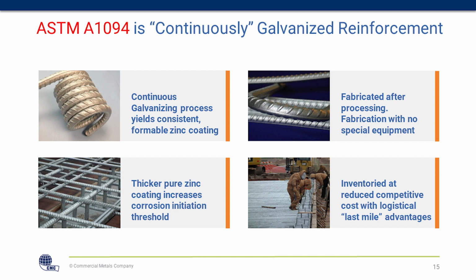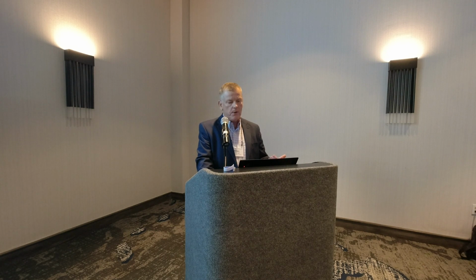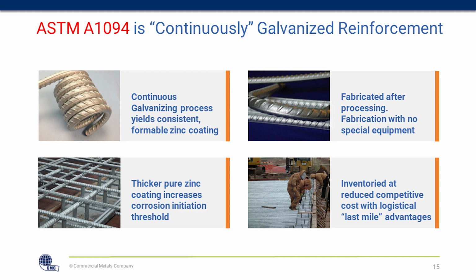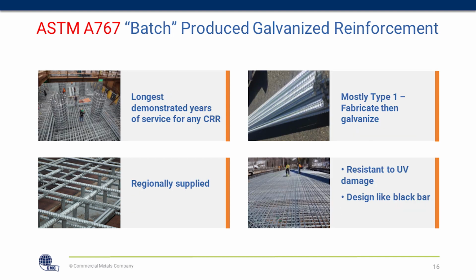It's still hot dip galvanized at 830 degrees, but it's very similar to the hot rolled steel coil sheet process that maybe some of you have seen in one of those really innovative facilities where they make steel coil for the automotive industry. And the key thing with this material is it can be fabricated after it's been processed. So there are some logistical advantages there. And then the batch process is one that we've seen for a long time. There are 2 classifications for it.